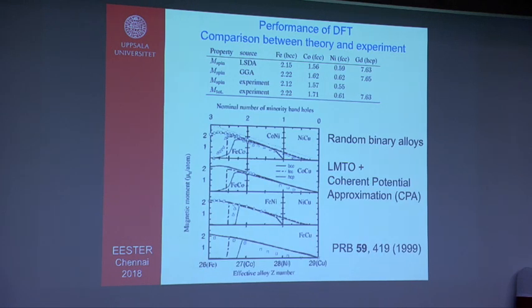These are now for more complex cases. These are random binary alloys, and you need certain techniques to treat these random alloys. Let's not go into that. For example, here the coherent potential approximation was used. Let's say this is the iron cobalt alloy. Average magnetic moment is plotted here as a function of effective alloy number. That is basically you alloy between iron and cobalt. You change the concentration and you go from this side to that side. Let's look into the iron cobalt part only. The bold line is the theoretical calculation for the BCC phase, and these circles are the experiments. This is a fantastic agreement between theory and experiment for iron cobalt. They really follow the theory curve. The experiments and theory are right on top of each other.